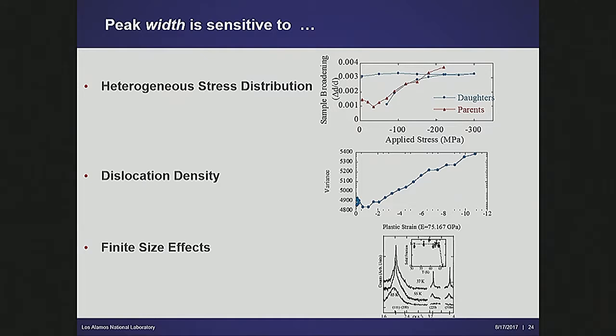Although we don't spend a lot of time doing it, you can also pull information out of peak width. It's the subject of a talk, a rather more sophisticated talk. We spend a fair amount of time at Los Alamos relating peak widths to dislocation densities. You can do that on any high resolution instrument, such as the ones that you have here. You can relate this sort of dislocation density to radiation damage. It's another engineering related problem.